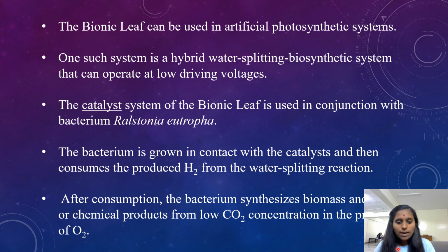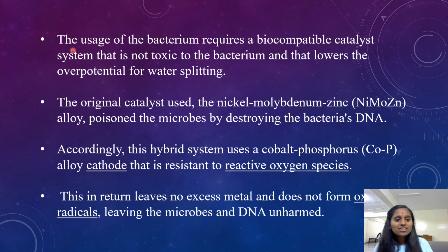After consumption, the bacterium synthesizes biomass and fuels or chemical products from low carbon dioxide concentration in the presence of oxygen. The usage of the bacterium requires a biocompatible catalyst system that is not toxic to the bacterium and that lowers the overpotential for water splitting. The original catalyst used, the nickel molybdenum zinc alloy, poisoned the microbes by destroying the bacteria's DNA.